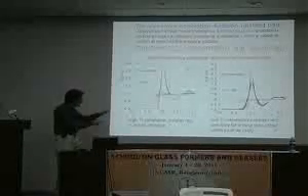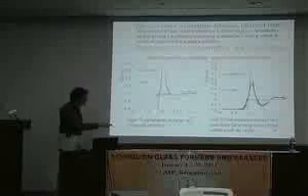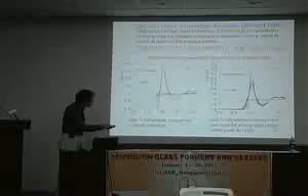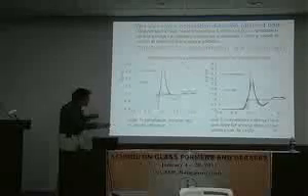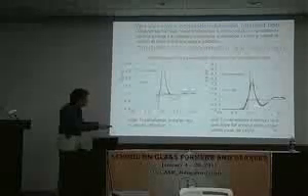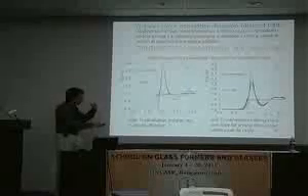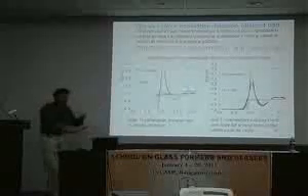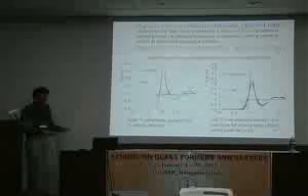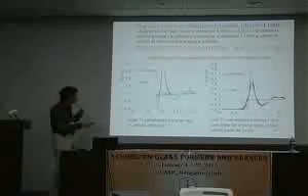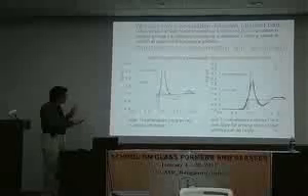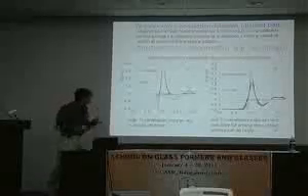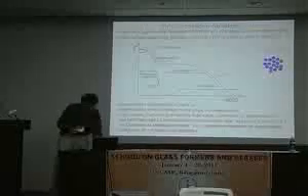Here it was filled up in a very continuous way, whereas here you have a small peak, which is due to particles that were sitting here jumping to the position of the particle that was sitting here, but of course that particle has to leave this place before. Okay, so you see quite a significant difference between the distinct Van Hove function at high and at low temperatures.